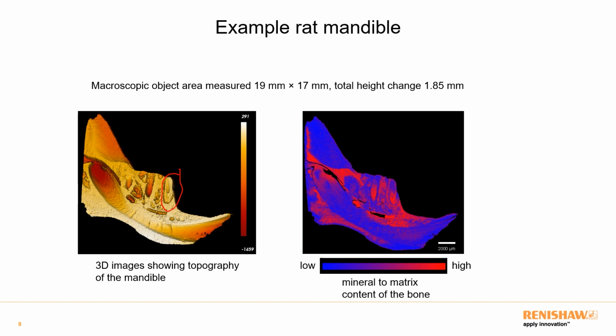Obviously, at the same time, we're collecting Raman data. And here, I've just created a simple Raman image, and this just shows the mineral to matrix content of the bone. So when I'm talking about the matrix, I'm talking about the organic components. And when I'm talking about the mineral, I'm talking about the apatite, so the presence of the phosphate band. And this gives us an indication of the variation in the structure. Clearly, there are significant variations across the whole mandible, and this is due to the different functional parts of the structure itself. But this is a really fantastic image, and I really love it.